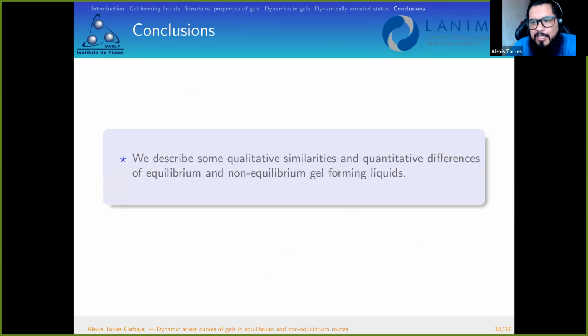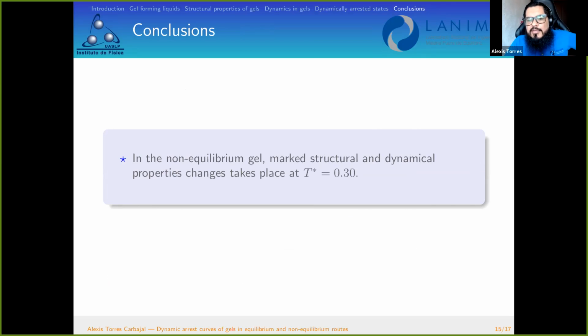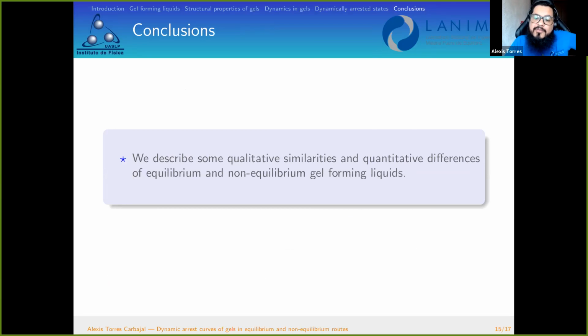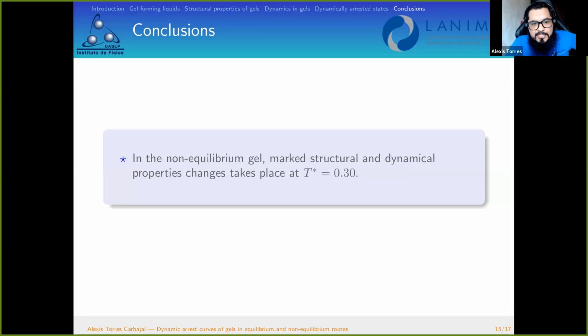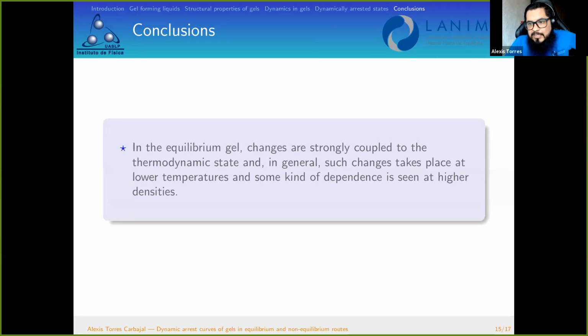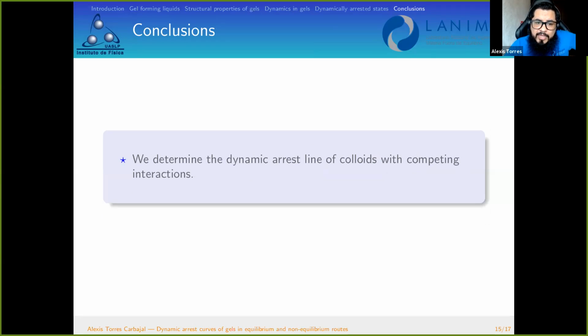Let me mention the conclusions. The conclusion of this work is that we describe the similarities and differences of the equilibrium and non-equilibrium gel-forming liquids in terms of their structural and dynamical properties. We found that the Lennard-Jones has marked structural and dynamical changes in its properties at a certain temperature that is not seen in the case of the Lennard-Jones with a Yukawa tail. And in this case, we can use this information to determine the dynamic arrest lines, and for the first time, I think, for this kind of system with competing interactions, like the Lennard-Jones with the Yukawa tail.